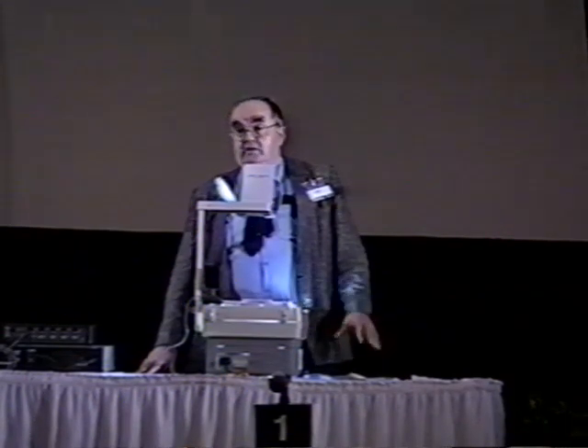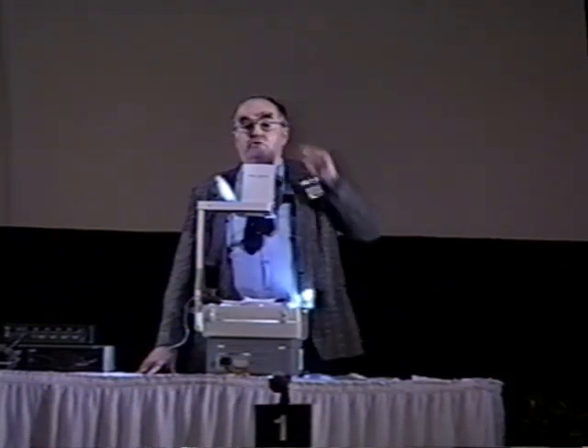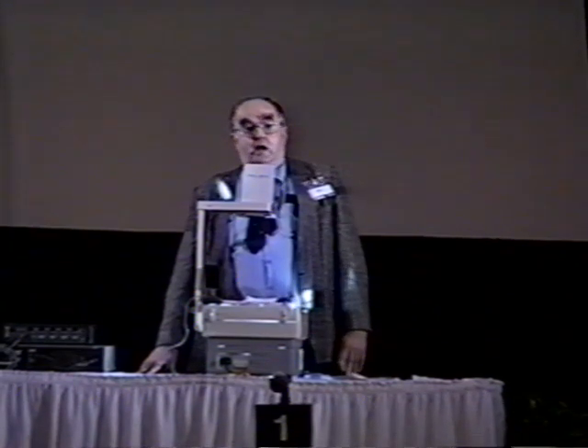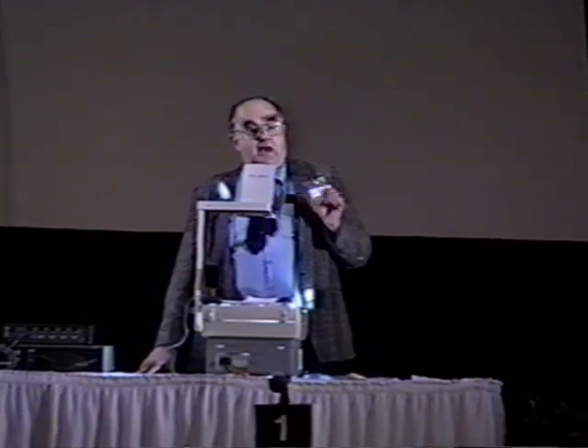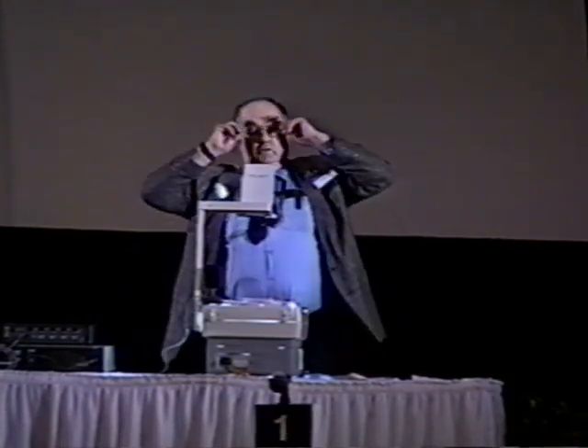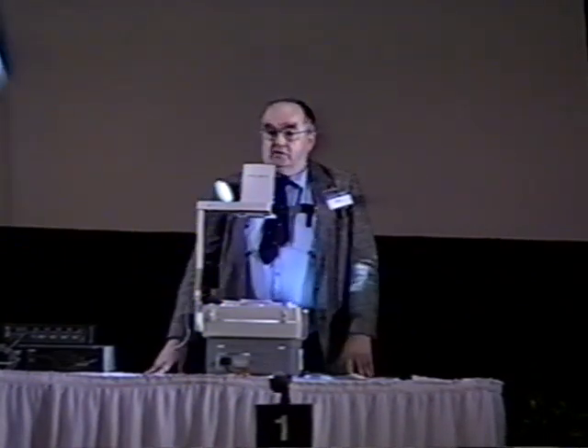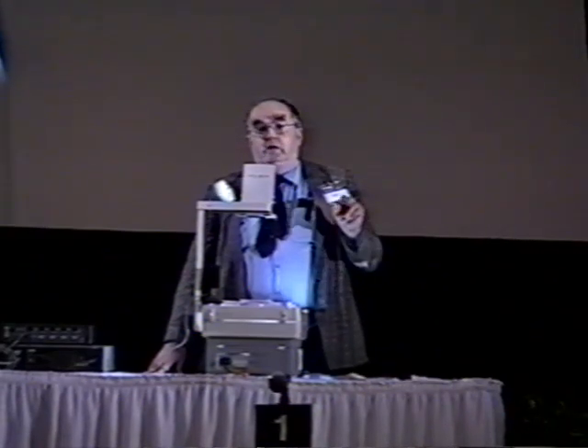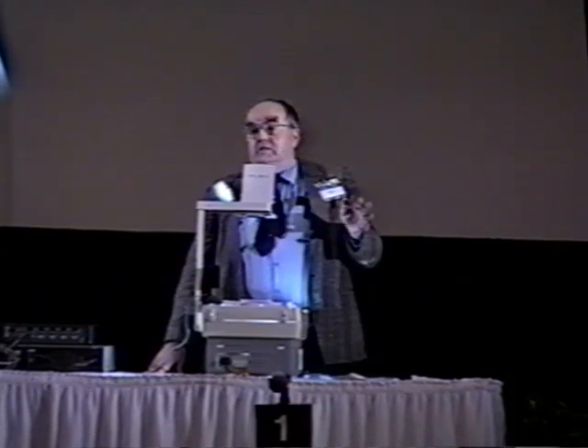Now, if it was about the same, a degree or two higher, or sometimes lower, that was no result. Only if the temperature with the deuterium was at least 5 centigrade higher than with hydrogen would I call it a positive result. And the positive results were few and far between initially. But I finally found a set of catalysts, all a type of family out of this huge, vast potential supply of commercial catalysts known to be active in hydrogenation, that would work. And I got temperature rises of deuterium over hydrogen of at least 5 centigrade, usually 7 or 9, and sometimes as high as over 20.